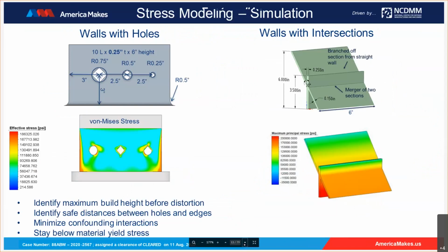If you go to the next chart, this is just a snapshot of the similar simulation strategies that we employed for the second and the third features as well. So we looked at the walls with holes and walls with intersections, and you can see, depending on what kind of features we're using, you might end up with different regions which are high stress or low stress zones. If you go to the next chart, Neil.